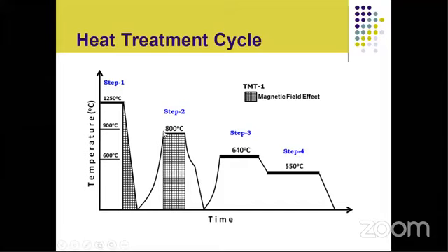And after a certain period of time, when it attains a maximum length along the field, it may break and this process continues. For a certain period of time, we apply the magnetic field, like in our case, we apply the magnetic field at 800 degrees Celsius for only 10 minutes. Although we have tried a lot of others, but I am quoting here for 10 minutes. Then material is again cooled.